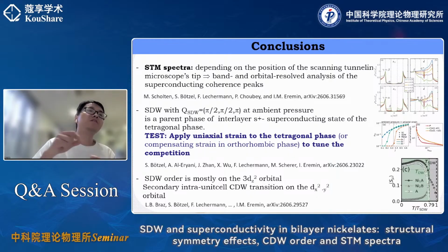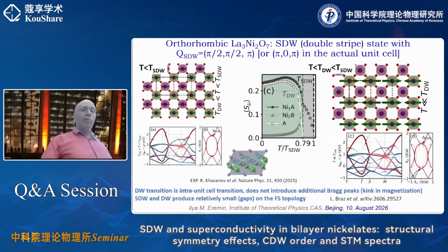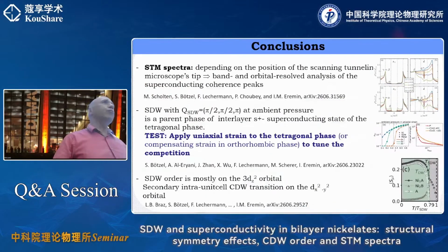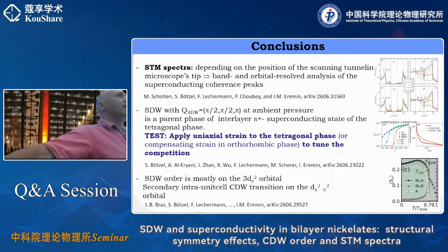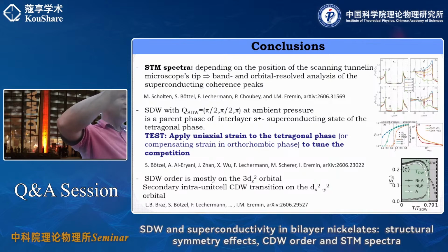So how about this temperature dependent behavior? Oh, sorry, the pressure dependent behavior of this. Yeah. So we don't have that, of course. Basically, we tried to do different linearizations as a function of pressure. But the problem, it turns out, is that the changes are so little that when you try to do linearization for different pressures, you don't get a clear trend. So then we just took this crystal field splitting to be a parameter. And I remember that if you tune it in such a way that the charge density wave transition is going down, whereas the spin density wave transition is going up, you can find this regime.